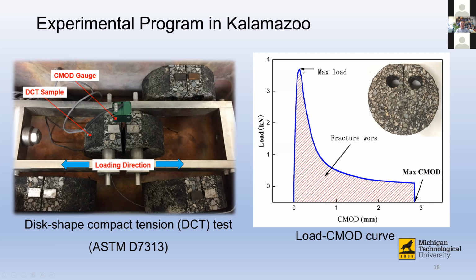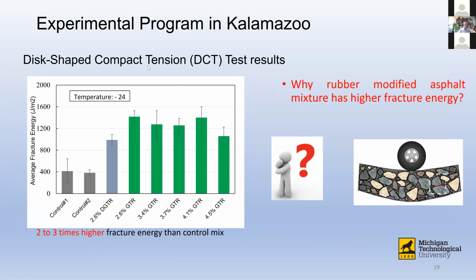And from this curve, we can find out the area underneath it. Of course, we can use a lot of ways to calculate that. So this area here is called fracture work. Let's say if rubber asphalt versus non-rubber asphalt, of course, we assume rubber asphalt will have much higher fracture work. That means in order to crack the sample, you need a lot of work or a lot of energy to crack the sample. So we'll see what the results look like over here.